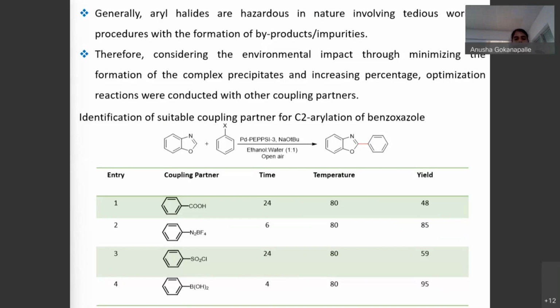We have already investigated that Palladium PEPPSI 3 is the best among all other Palladium PEPPSI complexes. That is why we directly added Palladium PEPPSI 3 catalyst and sodium tertiary butoxide, which is the best condition for the formation of C2 aryl substituted benzoxazole.